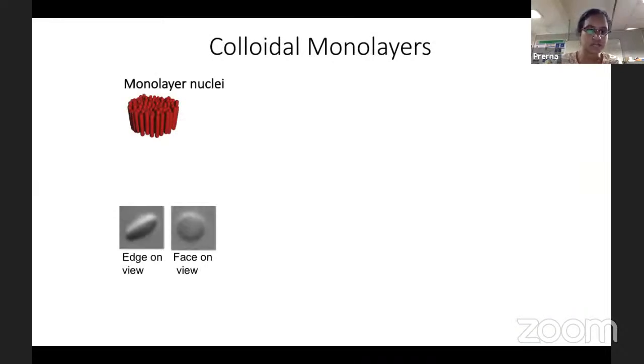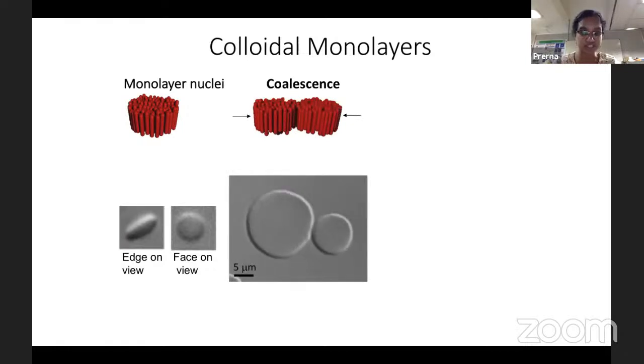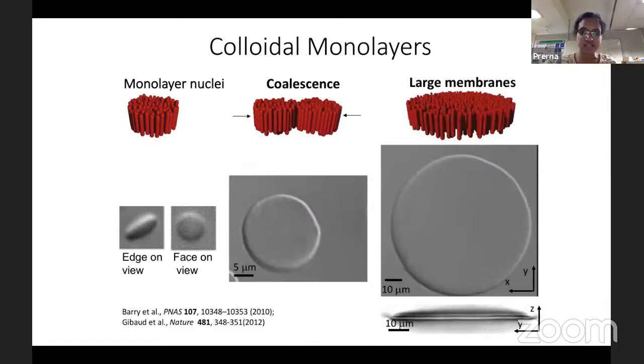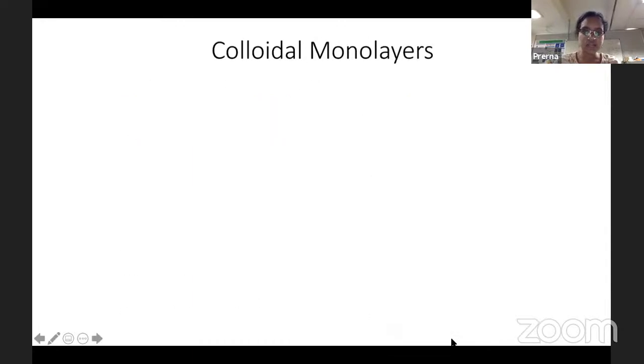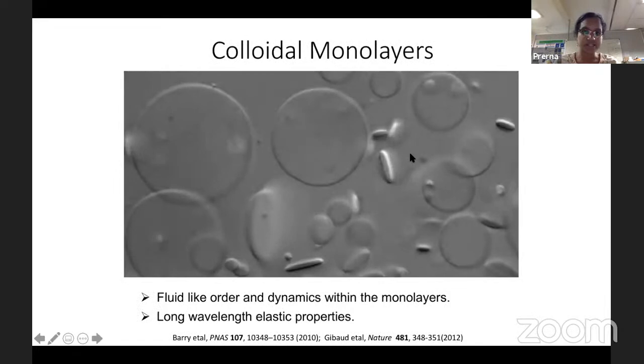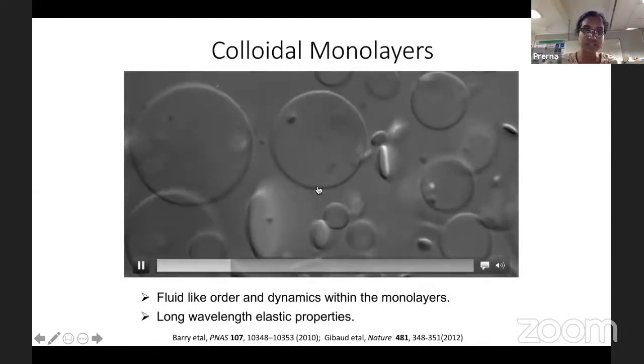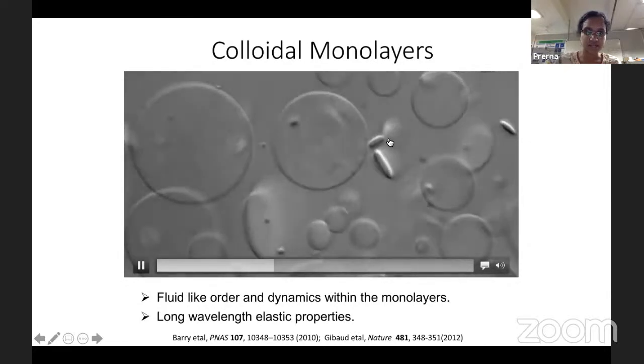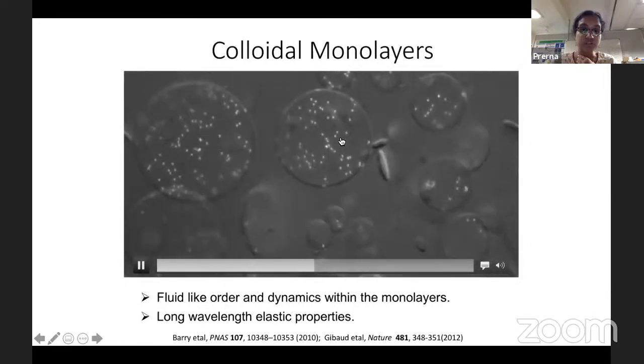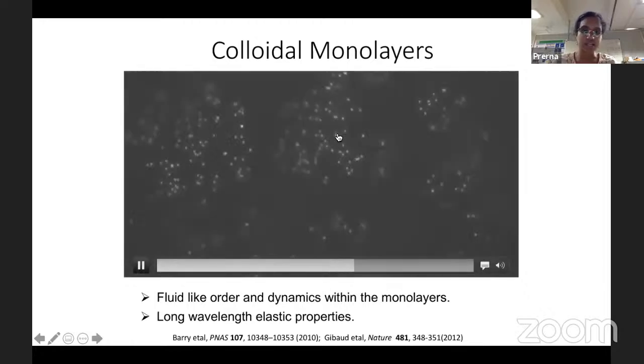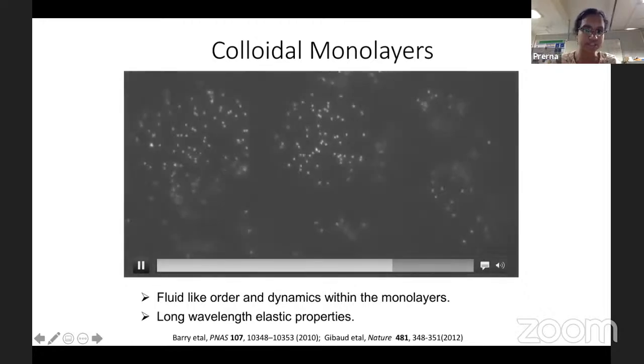This is how it looks under the microscope. If you look at the sheet from the top, it will look like a circle. If you look at it from the edge, it will look like an ellipse. If you have two sheets, they can coalesce with each other and make a larger sheet. So you end up with these really large sheets, tens of microns in diameter, one rod length thick. This is how colloidal monolayers look, right? Here you are looking at these sheets from the top, tens of microns in diameter, and I've labeled 1 out of 10,000 rods.